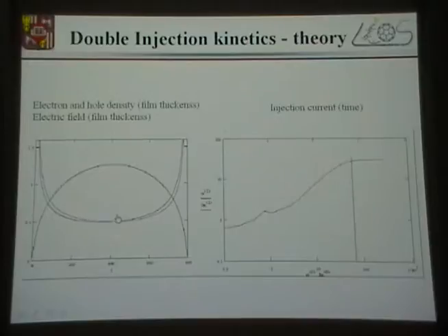You see, both electron and hole concentration really pumps up high, and the current still continues increasing, but then it saturates because the concentration has reached so high levels that the second order bimolecular recombination becomes extremely fast. This, again, is a well-known fact from Mark and Lampert, but the current saturates to a certain level again during double injection.